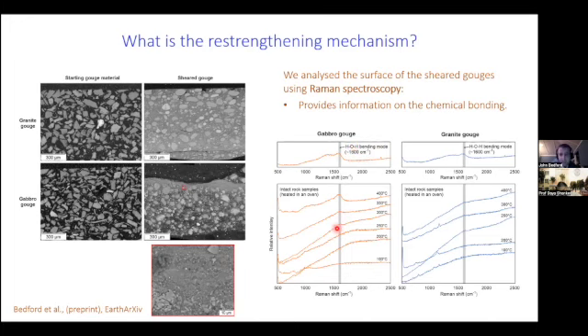What we start to see is the small peak appears at around 300 degrees for gabbro. In granite, it's less obvious, but we start to see maybe a small peak around 250. But these are the sort of temperatures we were reaching in the high velocity experiments. So it looks like we're getting some sort of chemical bonding change on the surface of our gouge materials caused by the high velocity slip. And we hypothesized that potentially it's chemical bonding that is happening quickly after the gouges stop shearing that is re-strengthening the materials.